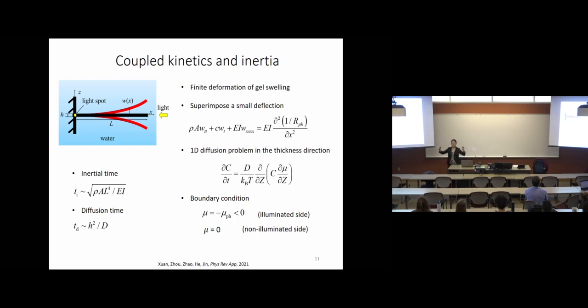We first consider the hydrogel undergoing equilibrium swelling. Then we superimpose a small deflection of the hydrogel with respect to the equilibrium state, described by this oscillation equation. W is the deflection, and the first term describes inertia, the second term describes damping, the third term describes elasticity. The unique thing is on the right-hand side, which describes a photo-induced moment. That's because I have light locally on one side but not on the other side. Therefore, I can create a water concentration gradient. Equivalently, it creates a photo bending moment, which is the term on the right-hand side.